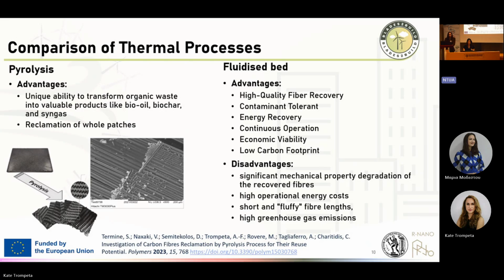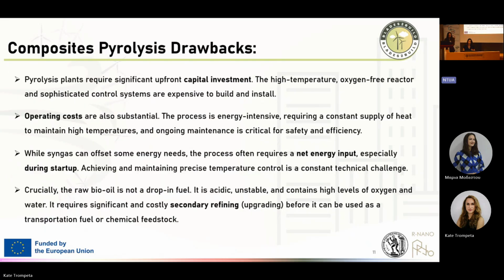However, there are some disadvantages, as for example, the significant mechanical property degradation of the recovered fibers, the high operational energy costs, that we get mainly short and fluffy fiber length and not a whole patch, and sometimes there are high greenhouse gas emissions. Also, pyrolysis has some drawbacks.